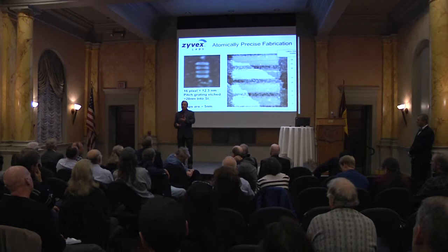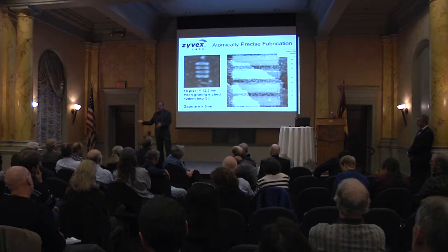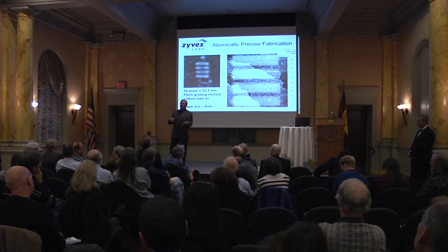And so there may be a space in there that affects the energy of the liberated hydrogen atom that would improve the ability to keep it from coming back to the surface. We're pretty sure it's bouncing off the tip, or at least the speculation is it's bouncing off the tip and coming back down. So maybe there's something that we can do to functionalize the tip to capture the hydrogen as it comes off and every once in a while shake that hydrogen off. There's a number of things we could potentially do there. It's a great question.